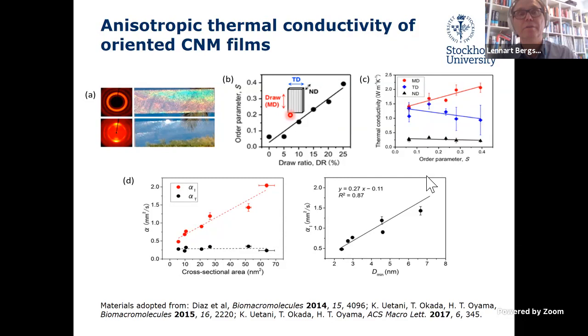So the thermal conductivity in the draw direction, in the transversal direction, and then in the normal direction. As you can see, the normal direction here does not really vary as the degree of order increases, but when it comes to the draw direction and the transversal direction, this changes quite a lot.